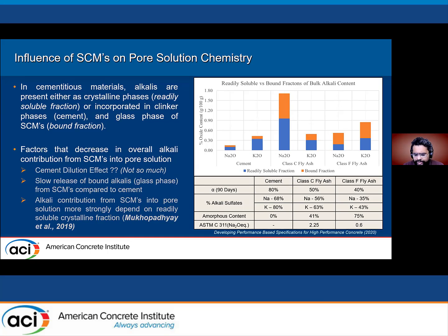Just a quick discussion on how SCMs influence the pore solution chemistry. Whenever we look at the bulk XRF data, we look at Na2O and K2O, the sodium oxide and potassium oxide. The value there is essentially comprised of two separate parameters. One is the crystalline phase, or the readily soluble fraction, which is usually available within the first 24 to 72 hours after the hydration reaction starts. And the second component is the bound phase, which is gradually released into the pore solution as the clinker hydrates or as the pozzolanic reaction happens.